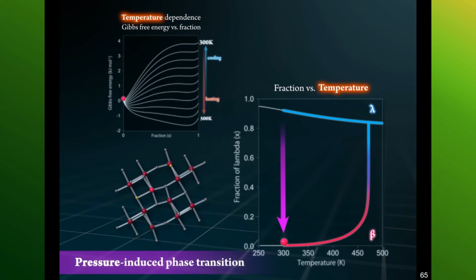Now, at this level of low pressure, the lambda and beta's thermal energy itself does not flip. The energy doesn't change that much. There's an energy barrier, a slight energy barrier which stops this. That's why pressure causes change. That's the mechanism. And this is not just by chance. From the beginning, we designed it this way. Otherwise, we wouldn't have found it.